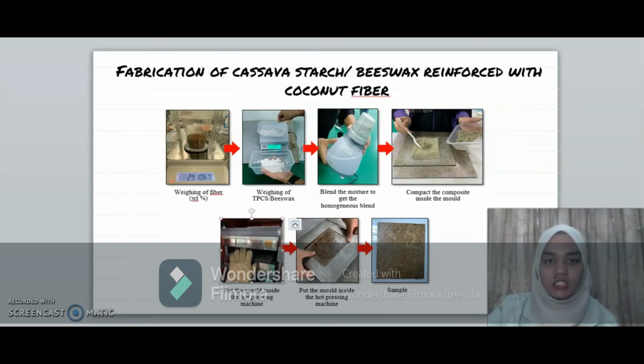Okay, this is fabrication of cassava starch and beeswax reinforced with coconut fiber. From the fabrication of cassava starch and beeswax, now we add coconut fiber to reinforce. So we weigh the fiber from 10% until 50%, and then we blend it with the mixture of cassava starch and beeswax. Then we compact it into the mold, and then put the mold inside the hot pressing machine, and we got the sample.